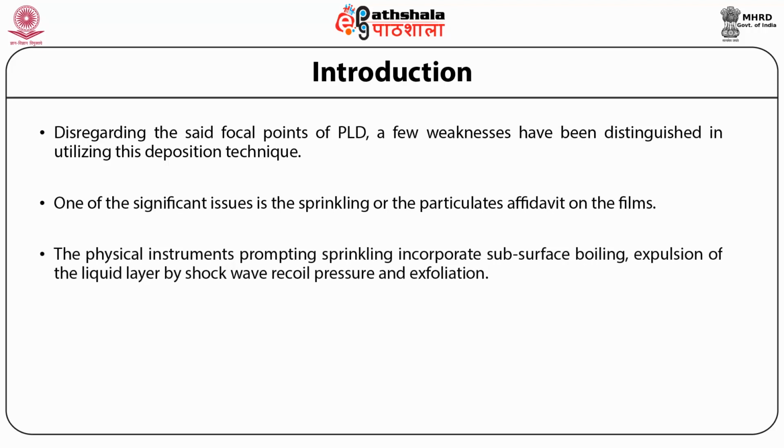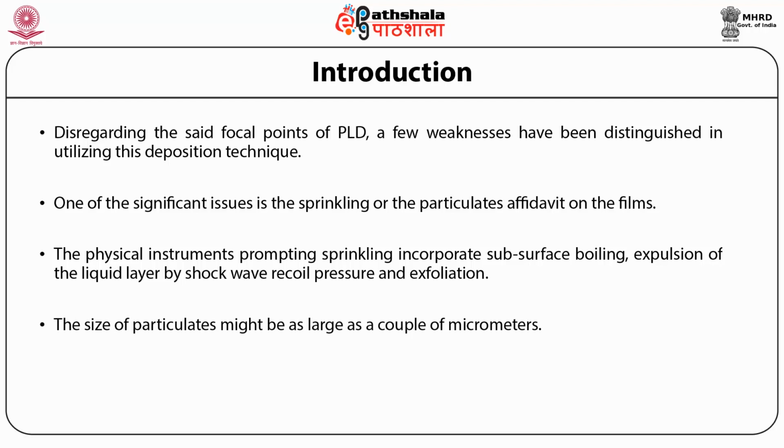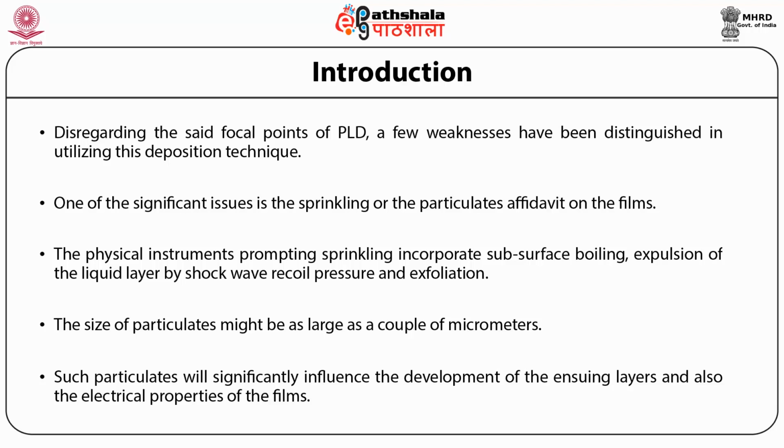The physical mechanisms leading to splashing include subsurface boiling, expulsion of the liquid layer by shock wave recoil pressure, and exfoliation. The size of particulates might be as large as a couple of micrometers. Such particulates will significantly influence the growth of the ensuing layers, and also the electrical properties of the films.